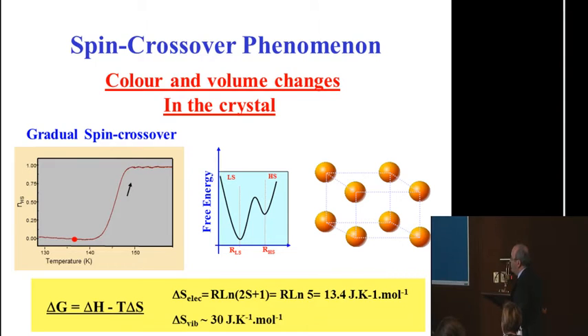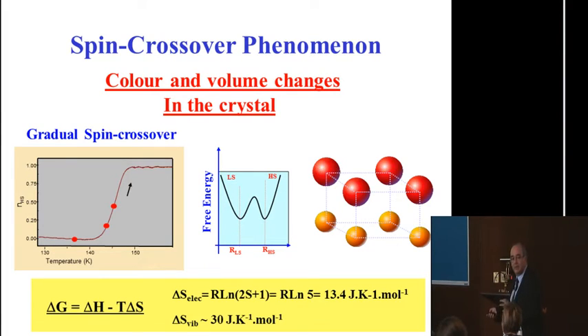That means that the only parameter here is temperature. So when you increase your temperature, you look at your double potential, you are stabilizing the high spin form like that. As soon as you increase your temperature, you are destabilizing your system, okay? So just because you are changing temperature, you are destabilizing your system. Everything is constant here, only temperature you have as a thermodynamical parameter of the system.